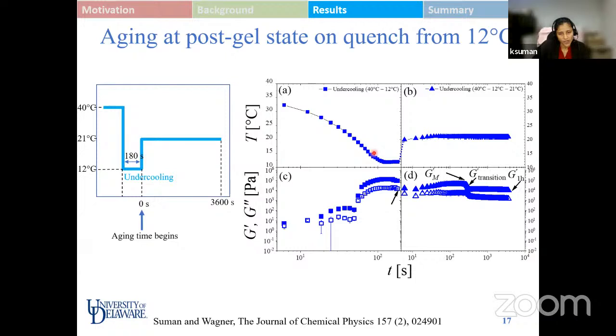So with this, we now want to understand what will happen if instead of quenching the system from a liquid state, we take it from a very arrested state to a target temperature. The schematic is shown on the left, which suggests that we take the sample, we start at 40 degree, take it to the lowest possible temperature for the system, which is 12 degree, and then from 12 degree, we take it to a target temperature. Let's say this is 21 degree in this case.